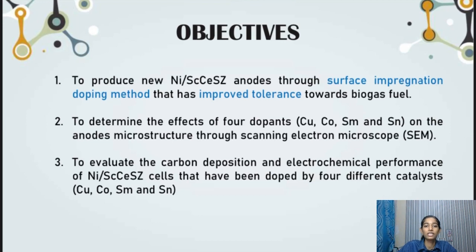Second, it is to determine the effects of four dopants, copper, cobalt, samarium, and tin, on the anode's microstructure through scanning electron microscope (SEM). And lastly, it is to evaluate the carbon deposition and electrochemical performance of nickel-scandia stabilized zirconia cells that have been doped by four different catalysts.